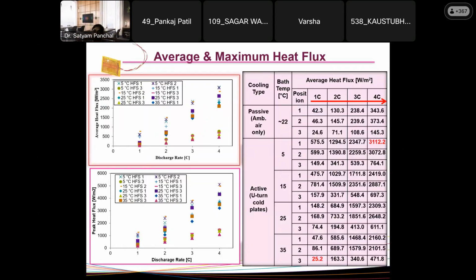Now, similarly, as I said earlier, on the other surface of the battery, we pasted a heat flux sensor which measures heat flux directly in watt per meter square, which is used for heat generation calculation. So average heat flux in watt per meter square for the air cooling method at 22 degree at 1C, 2C, 3C, and 4C is provided over here. And similarly for the water cooling method for 5, 15, 25, and 35 degree is provided over here, at 1, 2, 3 locations, and at 1C, 2C, 3C, and the 4C. And corresponding plots are provided over here.